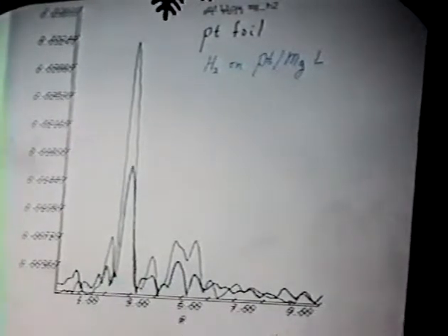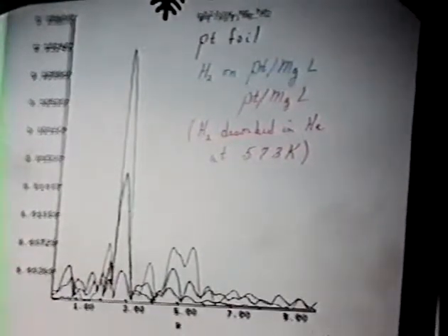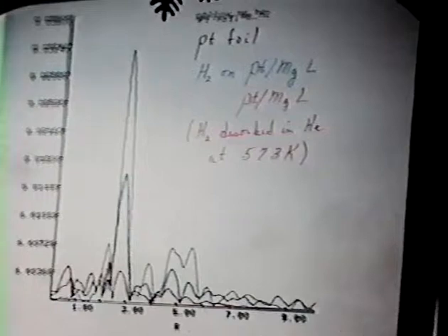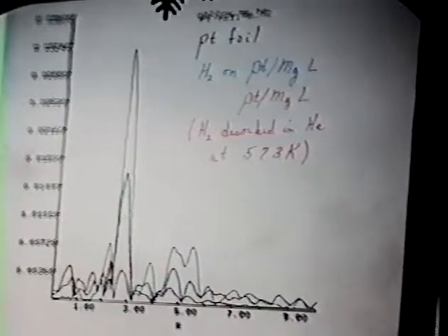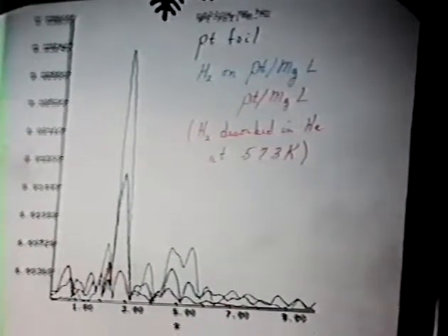And what happens is the bare particle seems to just fall all over itself or fall apart. There are no platinum-platinum distances. Either it's enough disorder that we've lost the coherence that you need for the XAFS, or in fact it's actually spread out over the wall. That's very surprising because it's hard to understand thermodynamically. What kind of interaction is there between the platinum and the wall that can overcome the platinum-platinum bonding? Either if you're going to disorder or if you're going to have it wet the walls. Either way, it's hard to understand. And yet, it's quite reproducible and in fact reversible.